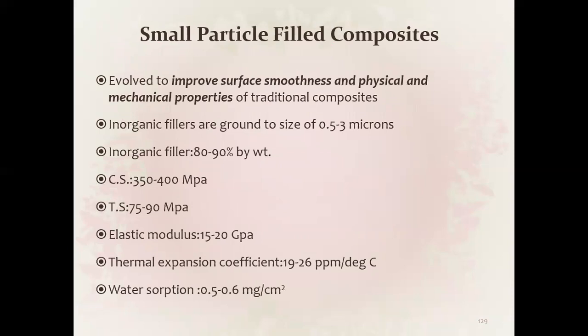Small particle fill composites were developed to improve surface smoothness and physical and mechanical properties of traditional composites. Inorganic fillers are ground to 0.5 to 3 microns, comprising 80 to 90 percent by weight. Compressive strength 350 to 400 MPa, tensile strength 75 to 90 MPa, elastic modulus 15 to 20 GPa.